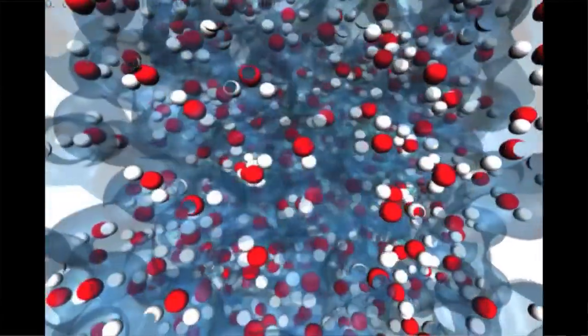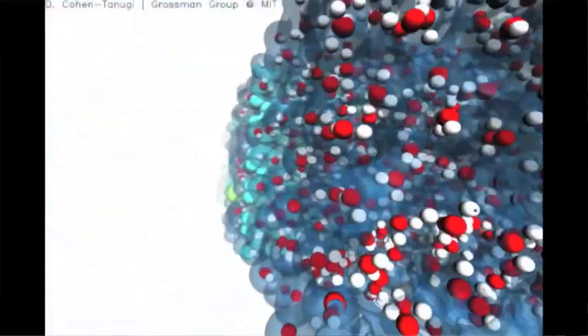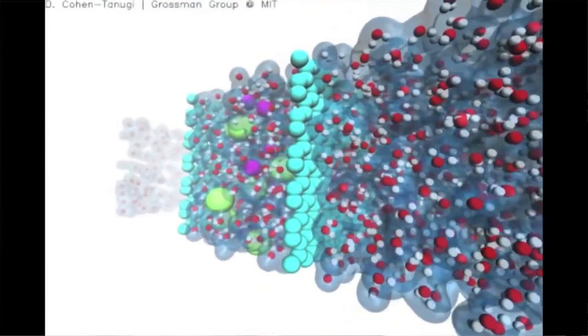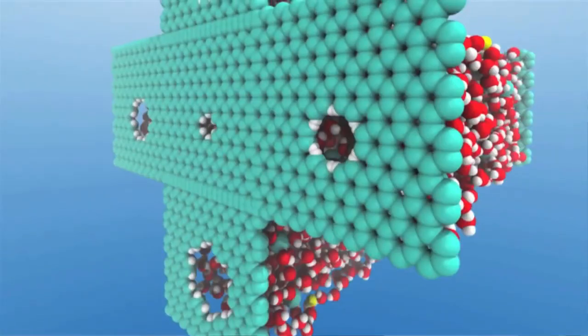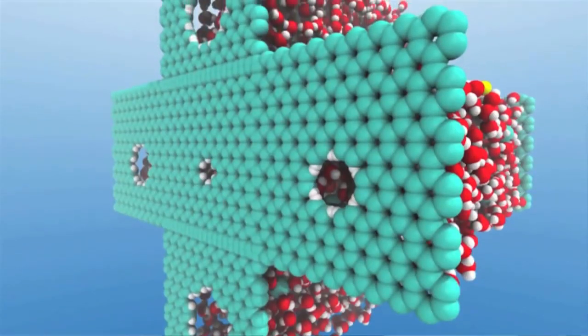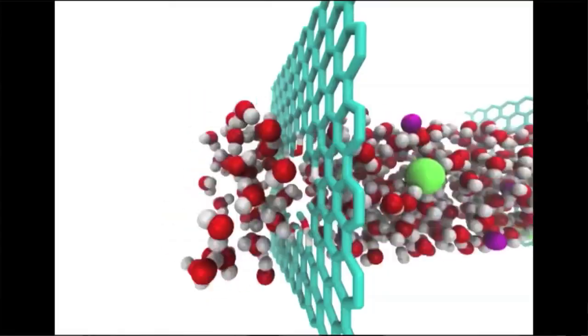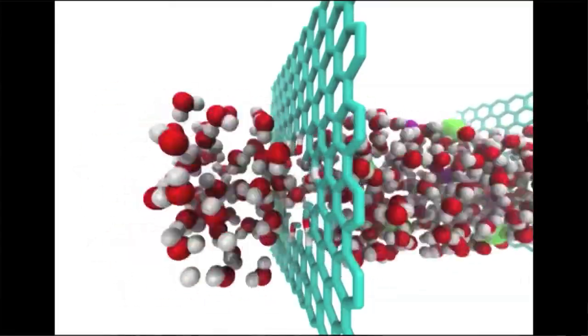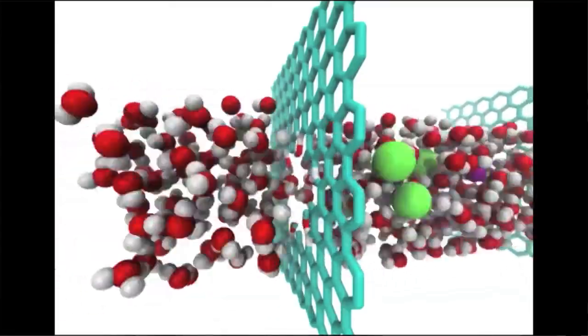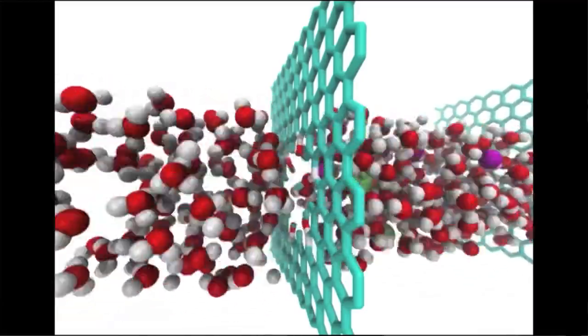And that means that if we were able to tailor the size of the pores within the graphene lattice, it might be possible to produce a very selective filter, or perhaps use smaller graphene sheets and use the pathways in between the sheets in order to tailor the porosity or the permeability of the membrane.